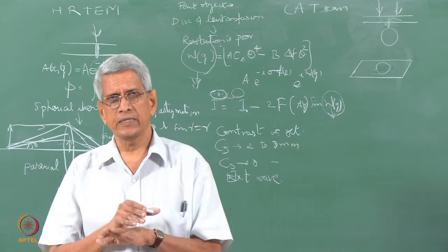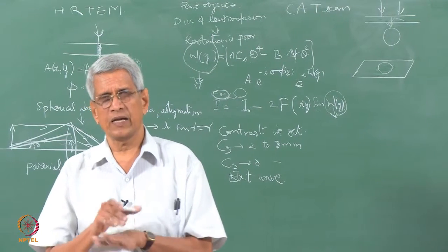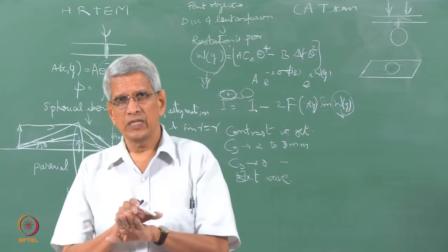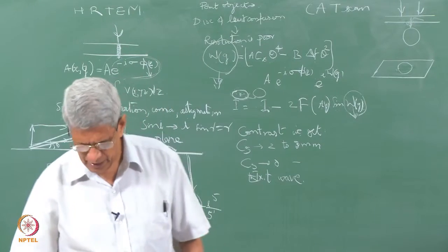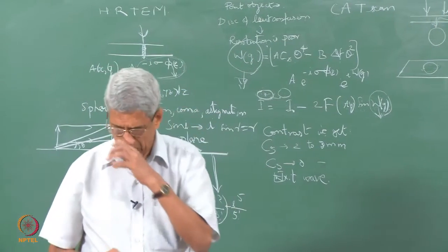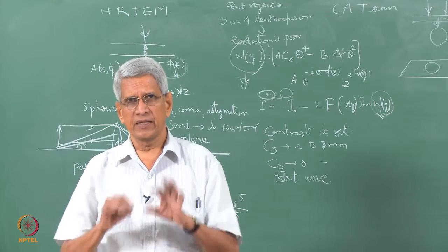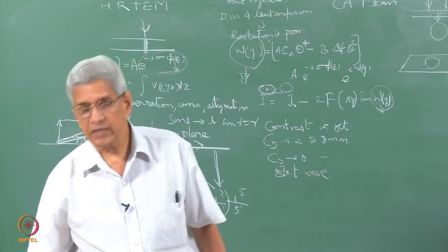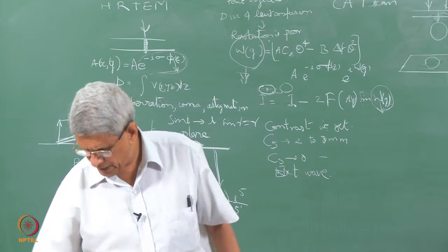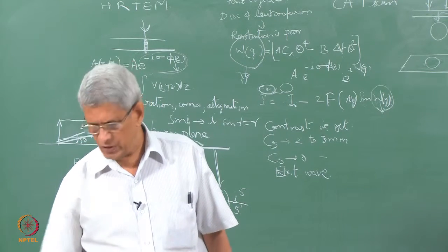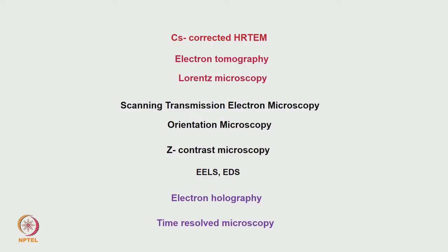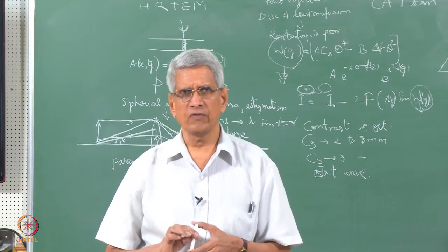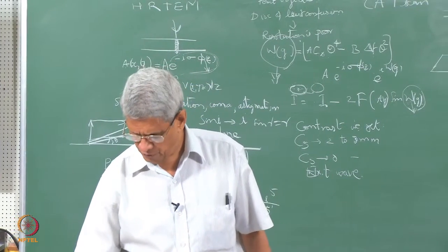Then all these images are stitched, because when the images are taken, the contrast will be continuously changing. There is software with which one can reconstruct a three-dimensional image of the object. That tells exactly what the morphology is of the different viruses, bacteria or various proteins which one looks at in the microscope. The same thing has been used especially in materials science also, to find out the morphology of the different types of precipitates which form during phase transformation.